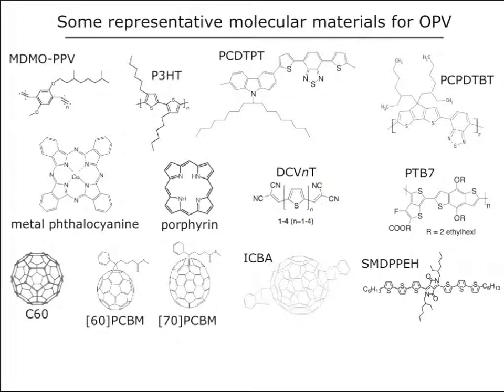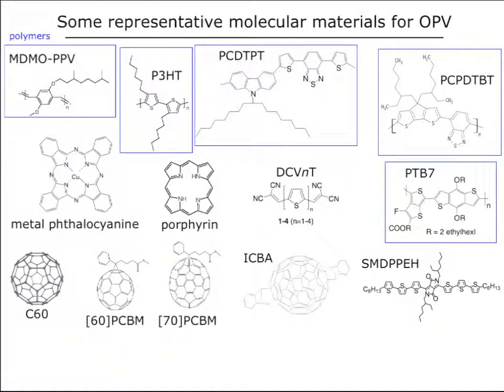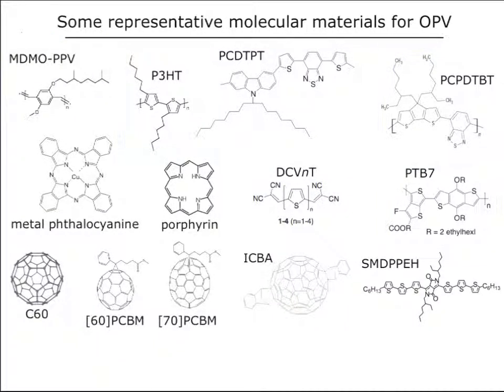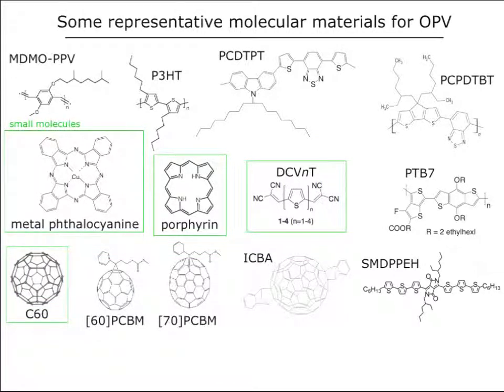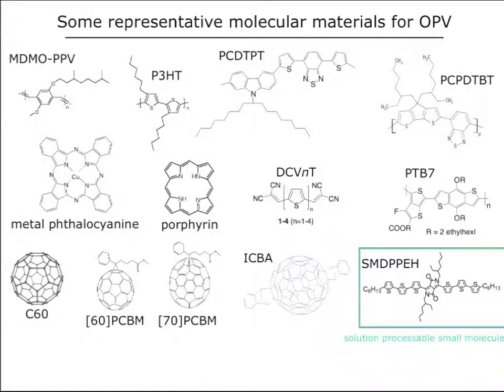Beyond that, we can think about some small molecule materials. This includes the phthalocyanines, the porphyrins, and oligomers that can all be thermally evaporated. And then we have some small molecules largely based on fullerenes that act like electron acceptors. And finally, a material that we can process from solution, but is also a small molecule. So there's a number of different ways to categorize all these molecules. One way is to say the blue squares are all polymers, so we can process them from solution, spin coat films, print films. The green squares now are small molecules that we can thermally evaporate and use vacuum deposition for. And then finally, this guy is something that is a small molecule that we can also do solution processing.